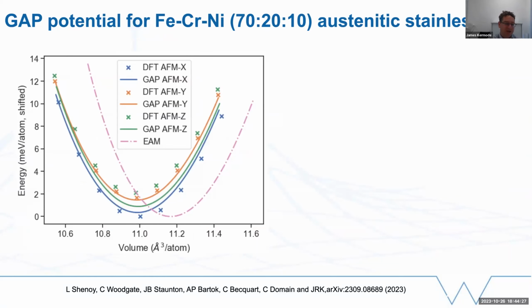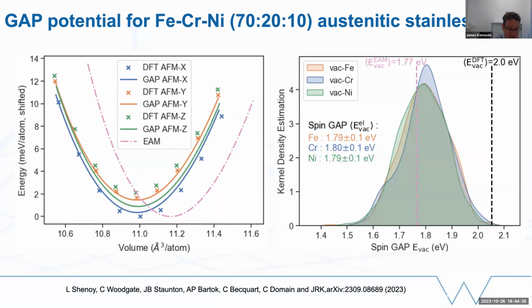And similarly, we can describe elastic properties. So energy volume curves come out nicely and are in good agreement with DFT calculations that include all the spin information. And we start to describe point defect energies more accurately as well. So we get an improvement in the description of the vacancy formation energy, for example. We can remove any kind of atom and we get the same distribution of formation energies, and they're starting to be in reasonable agreement with DFT.